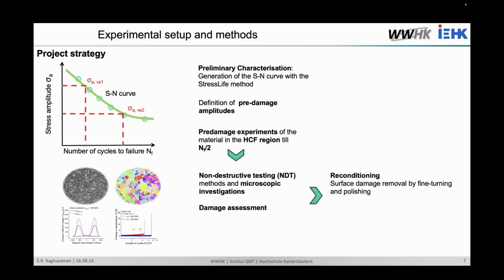And then we will think about reconditioning the material, that is, removing the damage that we have introduced. This is done here: the surface damage is removed by fine turning and polishing. The next step will be mixed HCF and VHCF loading of the reconditioned material.